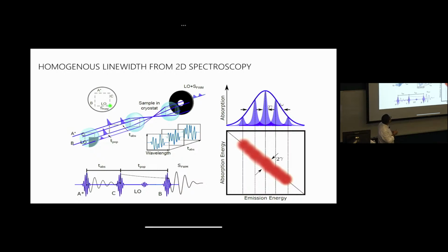And let's say that you bring in 3 pulses, you put them A, B, and C in the corner of this box. You focus them on your sample, and there's some time delay between each of these. Let's just think of this classically. The first pulse is going to see the electrons in the bulk in your sample. It's a femtosecond pulse. It has an electric field profile. That electric field is going to start driving the electrons, the oscillators, in phase. It's a very short pulse. The electric field is very well defined. It's going to start driving all the electrons in phase, and they're going to start oscillating. But then, either because they're very strongly coupled to phonons, or because of the scattering, if I'm an electron here and there's one there, we feel each other coulombically, that's going to scramble our phase. So there's a dephasing process, so-called dephasing.